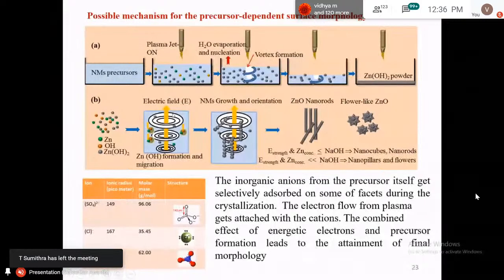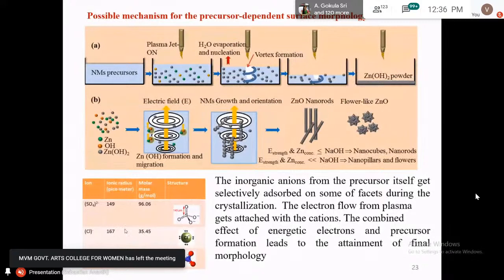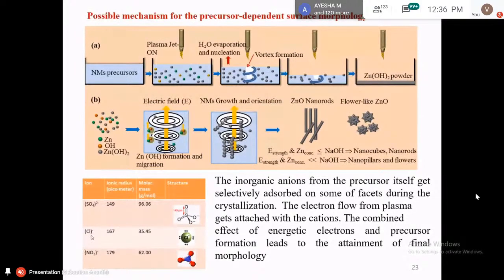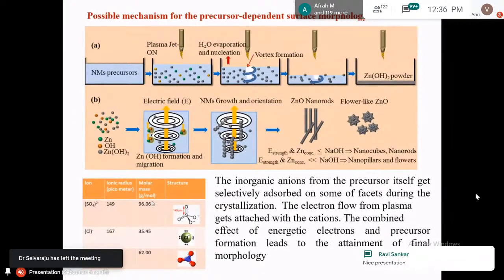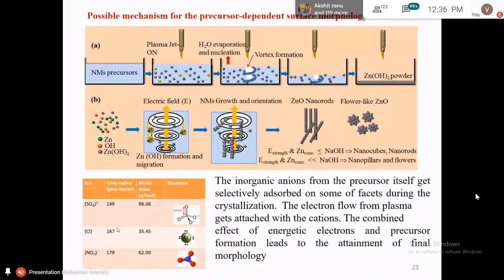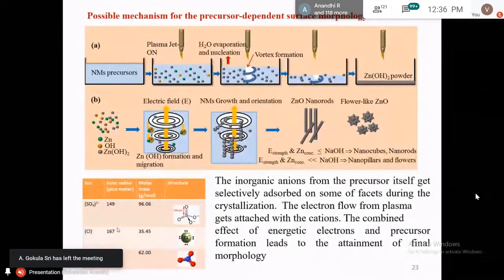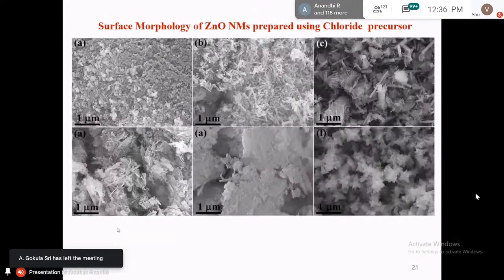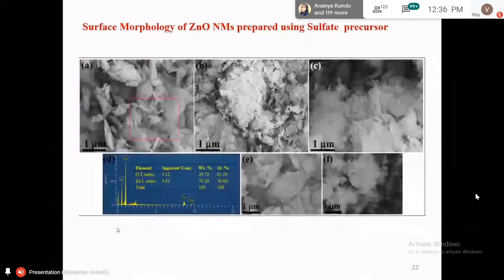In addition to this electric field, there is the nature of ions, because we took different precursors such as sulfate, chloride, or nitrate. Because of these ionic parameters, meaning ionic radius and molar mass, suppose you get a very high ionic radius, there may be a possibility of one-dimensional structure. So there is a complex interplay between the ionic radius, ionic molar mass, and the plasma species such as electrons and electric field. These all give a cumulative effect, which gives different nanostructures, such as one-dimensional, flower, or layer structures.